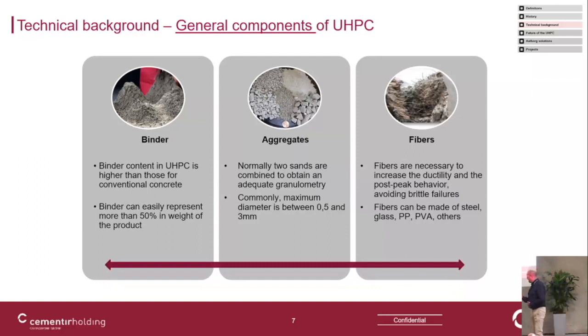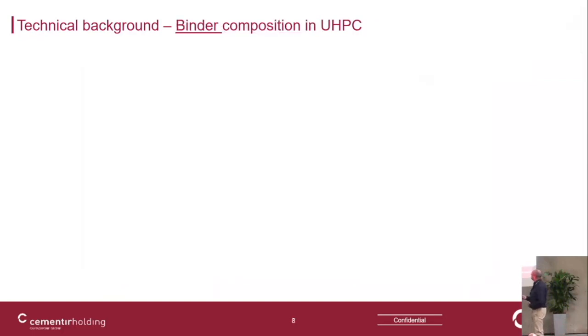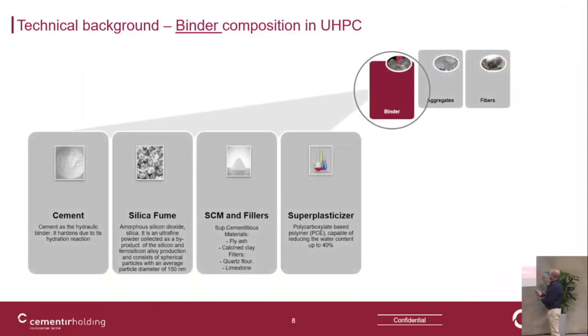If we now take a closer look at the binder itself, in the traditional UHPC, the binder is composed, of course, of cement, the Portland CEM I 52.5R, to have the high performance. Then you have the silica fume, which is a byproduct of silicon and ferrosilicon production. These particles are what we call ultra-fines, up to 150 nanometers, so in a finer range even than cement. And as filler, there are different possibilities: you can use fly ash, calcined clay, or even limestone filler.